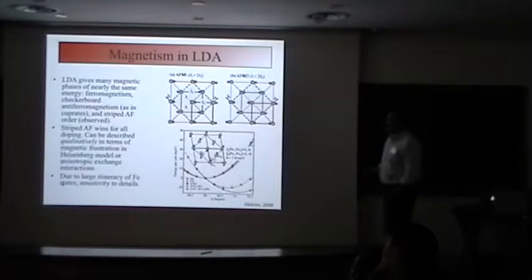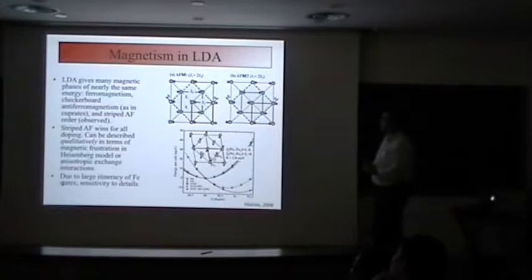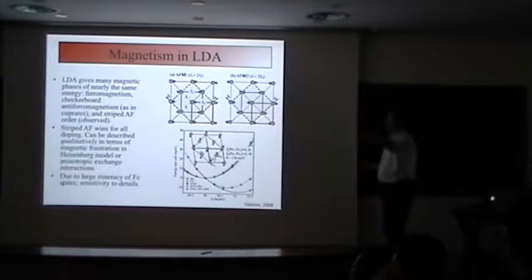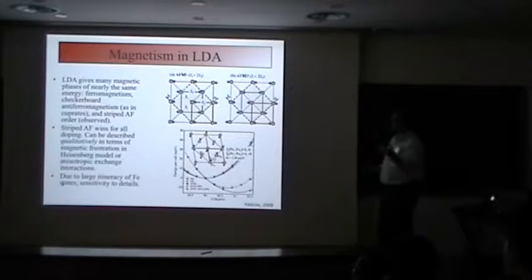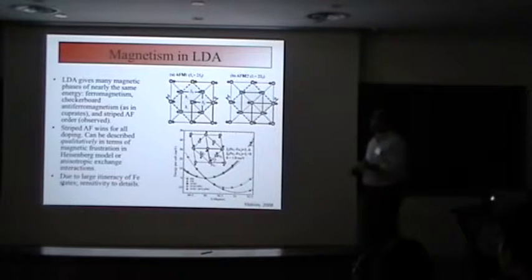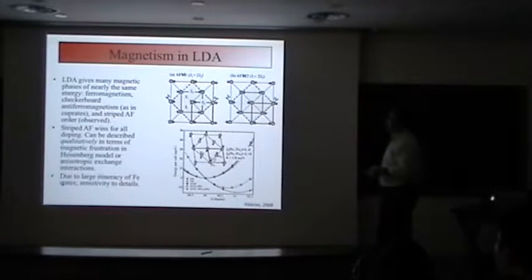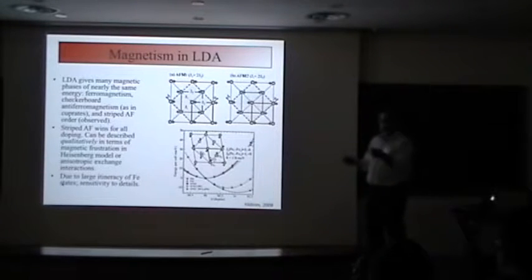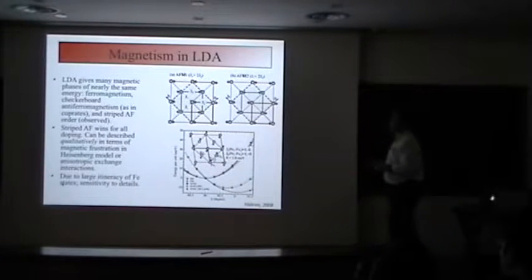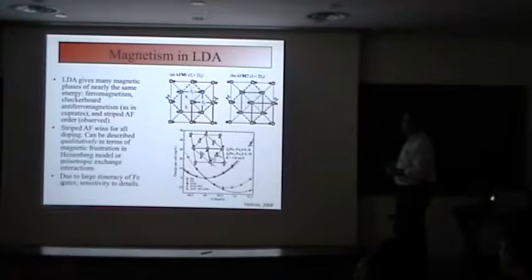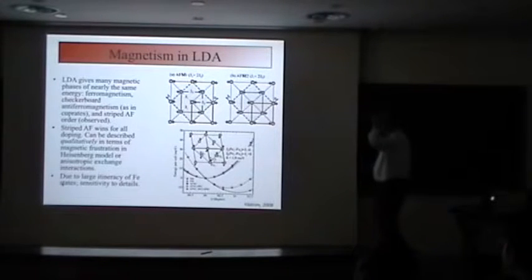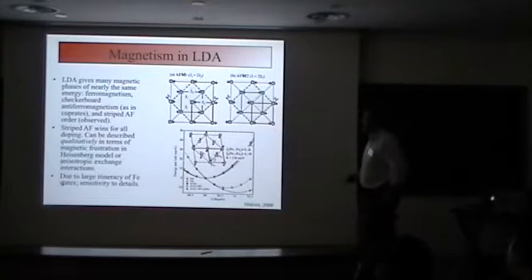That can be qualitatively described with a Heisenberg-like picture, where the long-range next-nearest-neighbor interaction going from iron to arsenic to the other iron could be quantitatively as large or larger than the nearest-neighbor iron-iron exchange. So that would favor an antiferromagnetic, collinear antiferromagnetic state if that hopping J2 is bigger than half J1. This is again connected to the large itinerancy of the iron states.